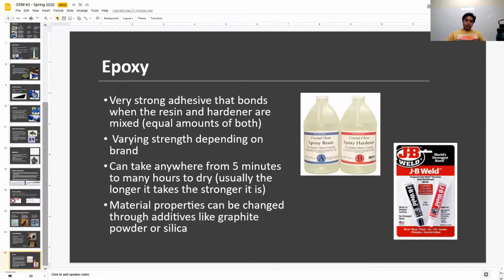Epoxy. So epoxy is pretty much how we get everything done on the team. If you want to make any kind of bond or make sure anything is held together, use epoxy. There are two types of epoxies that we use. We use JB Weld and we also use rock epoxy. The two main differences between JB Weld and rock epoxy is that JB Weld has a failure at heat of about 500 degrees Fahrenheit. Rock epoxy will fail at, I believe, around 300 degrees Fahrenheit.